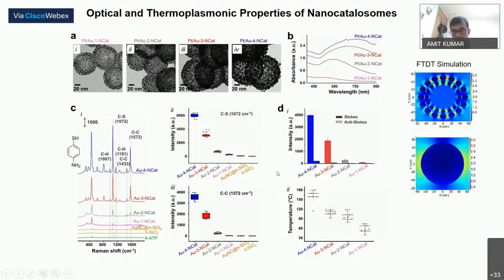And from previous reports, we could also calculate what will be the thermal localized heat generated during the laser irradiation. And we found that temperature can reach around 150 to 180 degrees Celsius in the largest structure when we shine laser. Although in the bulk solution, the temperature was very low, around 35 to 40 degrees Celsius, Raman spectroscopy suggested that the local temperature can reach very, very high.